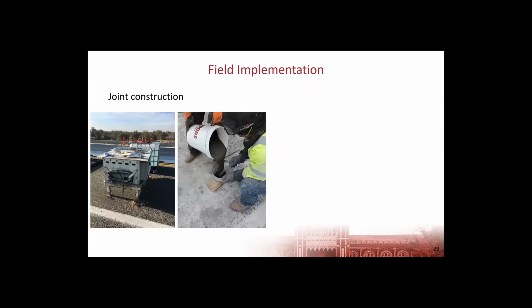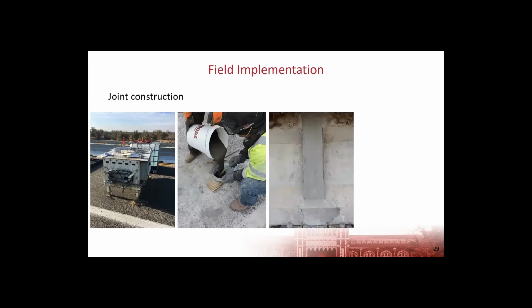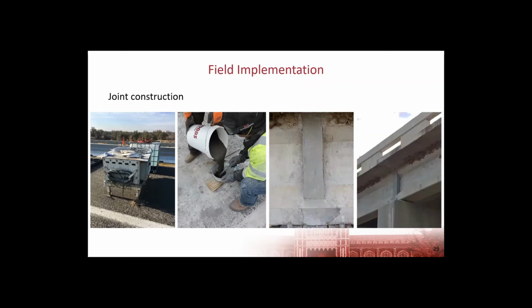It was placed through a 2.5-inch hole in the deck into each of those joints. So it had about a 5-foot free fall into each joint. It was a little difficult to place it through the hole, and I'll tell you a little more about that here in just a second, but we produced a very nice replacement joint using that UHPC. So you can see from a couple of different angles.